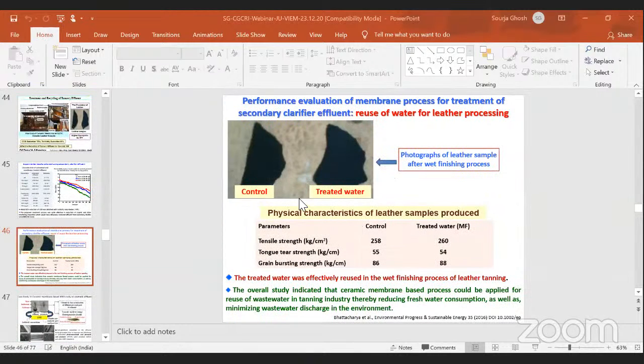So this is another sample of control and treated water for the leather sample, where these samples were analyzed for the physical characteristics. You can see comparable performance is obtained for the treated water sample in terms of tensile strength, tongue tear strength, and grain bursting strength. So all these parameters are comparable. This sample shows comparable mechanical strength, and the dye uptake was also found good. So this can be used effectively in the wet finishing process of leather tanning.